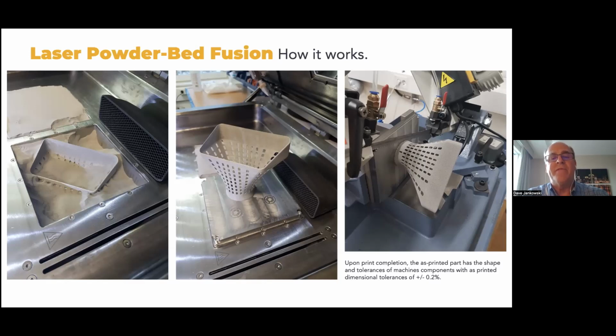In the middle photograph, you can see most of the unused powder being removed, the build plate being raised up. Since this is a micro welding process, the part is physically welded to the build plate. So what that means is after you remove the build plate from the printer, you would have to cut it off. And in this case, in the right-hand photograph, you see a bandsaw being used in order to cut off or remove the part from the build plate.